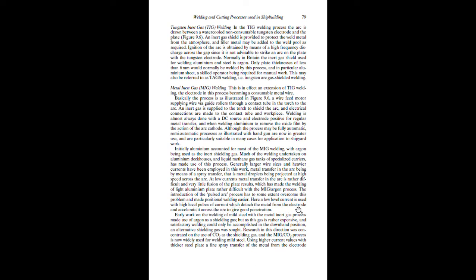Here a low level current is used, so as compared to the MIG process, here in the pulsed process, low level current is used with high level pulses of current which detaches the metal from the electrode and accelerates it across the arc to give good penetration.